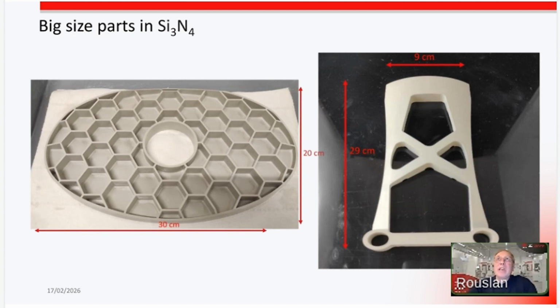To summarize, we are in the medium range of ISO 2768. So we are speaking of an accuracy of, let's say, 50-ish, 80-ish microns for the parts. But it will depend on the size. On a big part like this, of course, we will be more like 200 microns precision. Sometimes for parts with very, very tight tolerances, we need to produce the part and then machine it. Of course, it's difficult for silicon nitride because it's a very, very hard material.